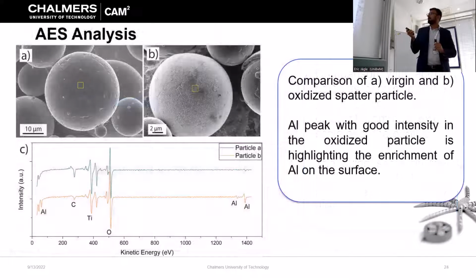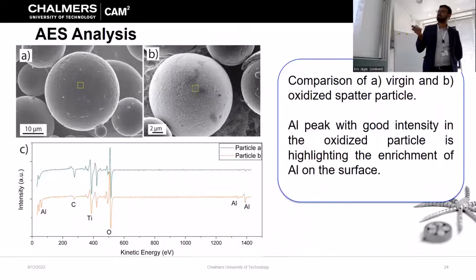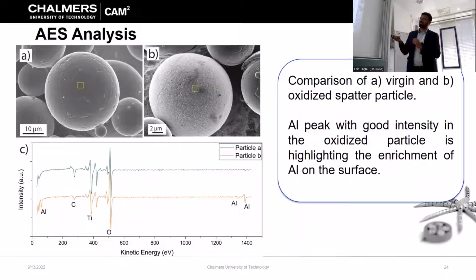Then we did some AES analysis and tried to compare the virgin and the spatter's surface. In virgin, you can see titanium and oxygen, and aluminum is a bit lower. What is the difference in the case of spatter? It is very much enriched with aluminum along with titanium. So the spatter and solidification or cooling process is giving aluminum a chance to go to the surface and oxidize.